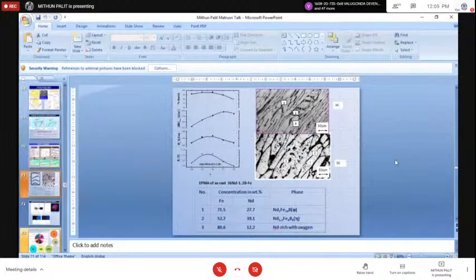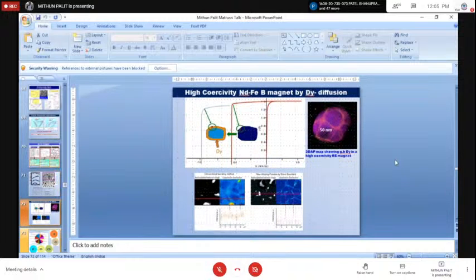You can see this microstructure. The dark color lines are neodymium rich phases, and inside you have 2-14-1. You can see how nicely they are shielded from each other, and this wall you can make stronger. For example, between two neighboring houses, you can make the wall of brick, make it of iron and steel, or make it of some kind of very strong stone. So depending on the material you use for the wall, the wall will be stronger or weaker.